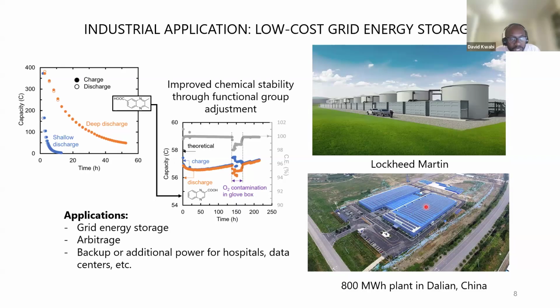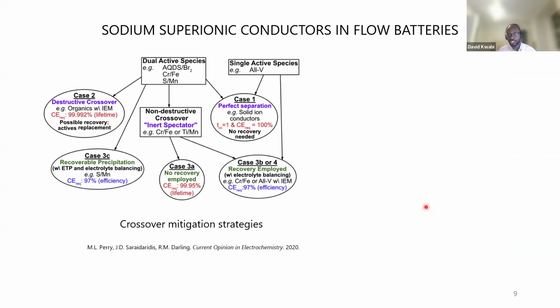Great. So I've mentioned quite a bit about designing organic molecules for use in flow batteries and essentially protecting against degradation, which leads to capacity fade. Another route for capacity loss in these batteries is crossover of active molecules from one electrolyte to the other. We ideally want the two electrolytes to stay separate and only have a single current-carrying ion go between both sides. But in reality, it's possible for there to be crossover from one electrolyte to another, which you want to avoid.